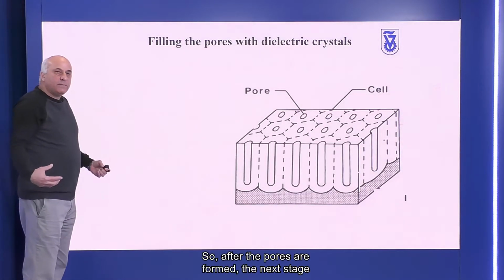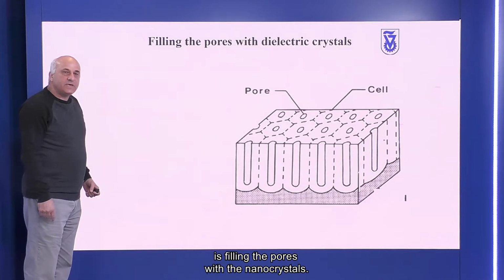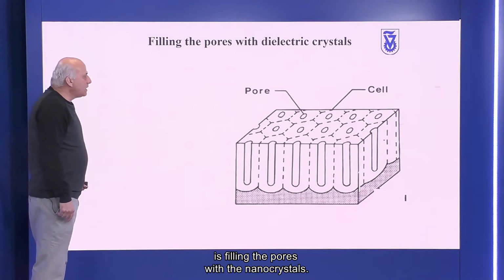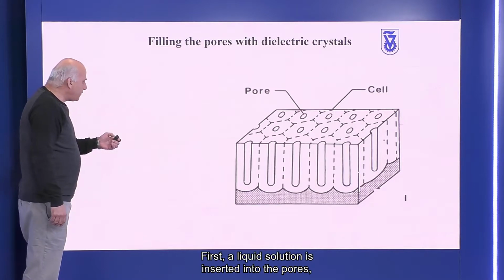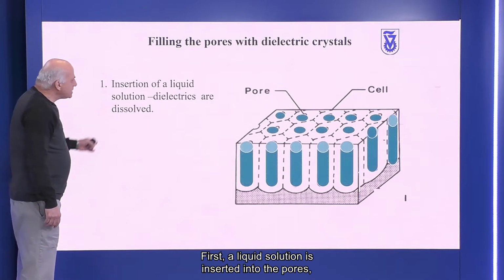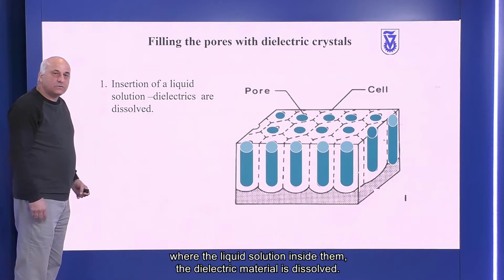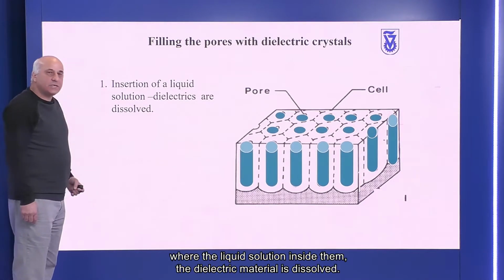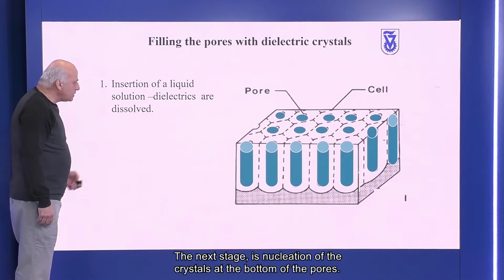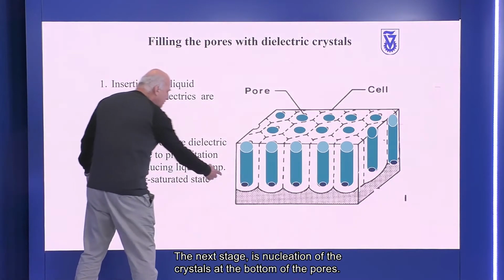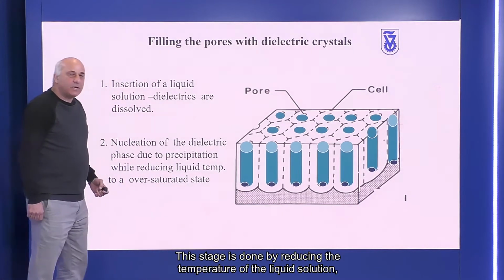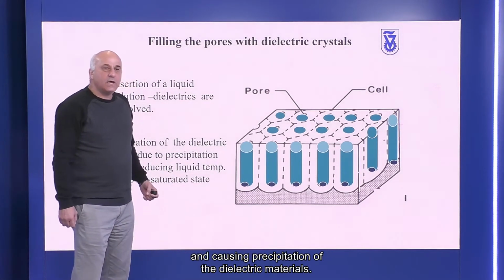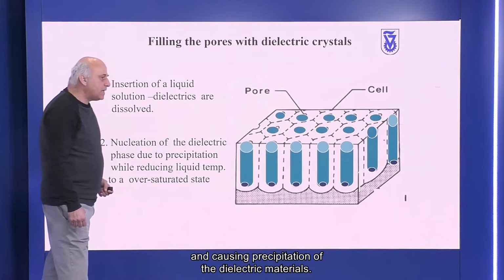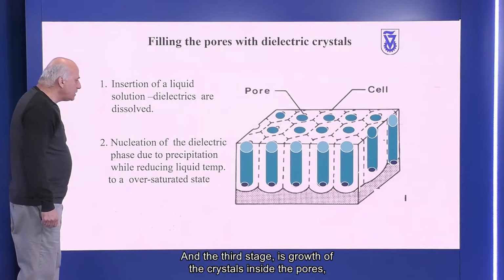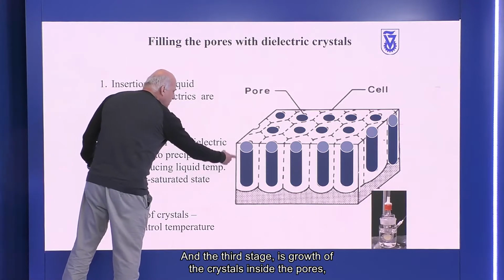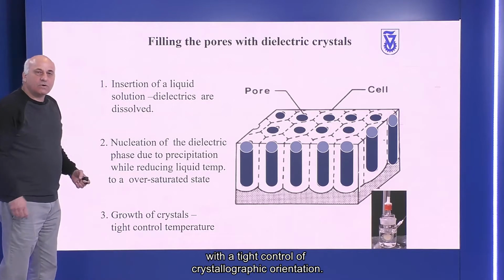After the pores are formed, the next stage is filling the pores with the nanocrystals. The process is as follows. First, a liquid solution in which the dielectric material is dissolved is inserted into the pores. The next stage is nucleation of the crystals at the bottom of the pores. This stage is done by reducing the temperature of the liquid solution and causing precipitation of the dielectric material. And the third stage is growth of the crystals inside the pores with a tight control of crystallographic orientation.